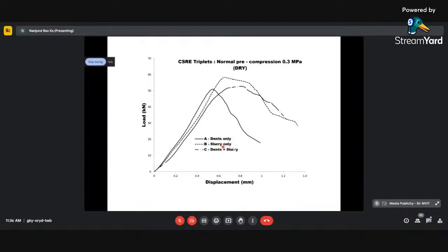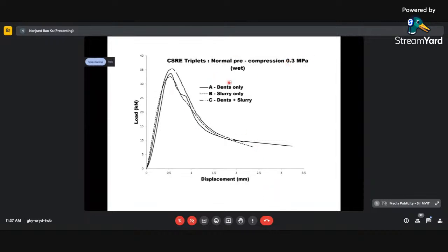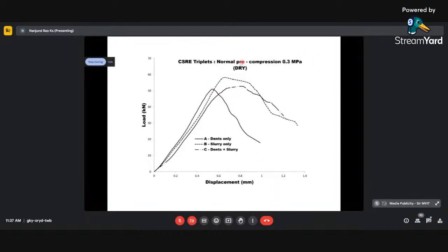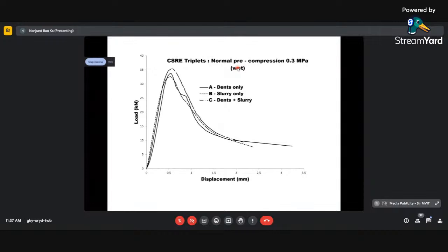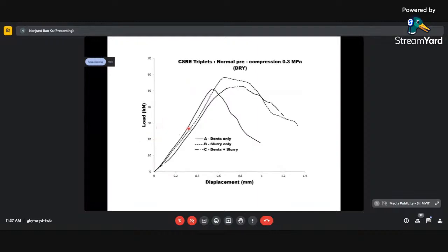For 3 different cases, only dents, slurry only, dents with slurry. And this is the response, the load versus displacement of the triplet shear test specimen. This is for the wet condition, this is for the dry condition. The same specimens were in the dry, that means about 2% moisture, whereas wet means saturated condition, where roughly 18 to 20% moisture will be there. And in this case, you will see the different enhancements in bond strength have no impact in the wet, whereas in the dry condition, there is a slight difference, and also ductility is much more in some of them. This is dents only, whereas slurry and slurry with dents are here. They behave in a much more ductile fashion with slightly higher strength also.